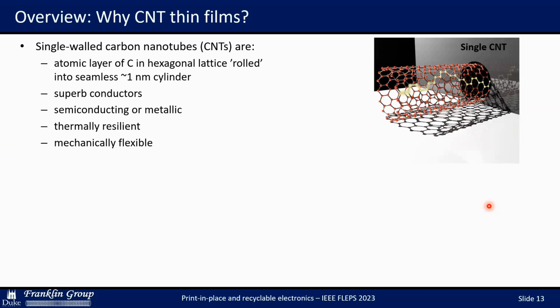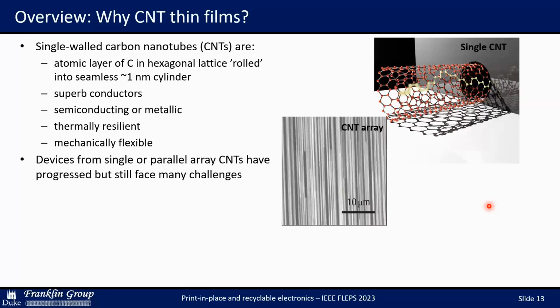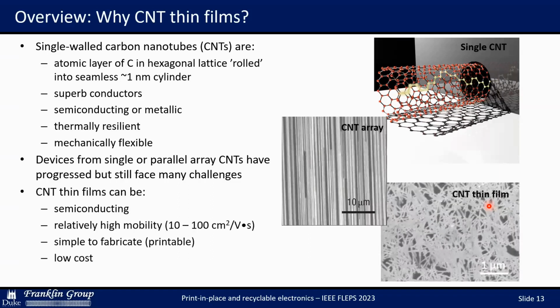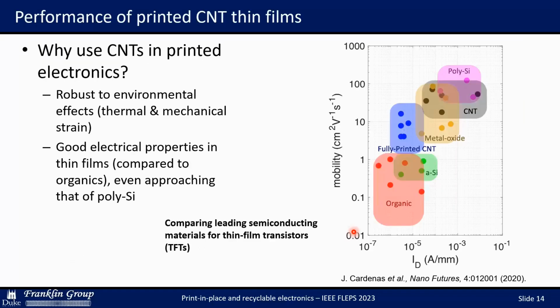So some of the early work was focused on isolating individual semiconducting tubes, but that evolved into the use of the nanotubes in arrays, and eventually, not exclusively, but there is a lot of work now in what we would call thin film nanotube-based devices, including those that are printed. And even though you're going to end up with a small percentage of metallic nanotubes present, when you're dealing with microelectronic thin film devices, the averaging effect of the dominant semiconducting presence yields a net semiconducting film.